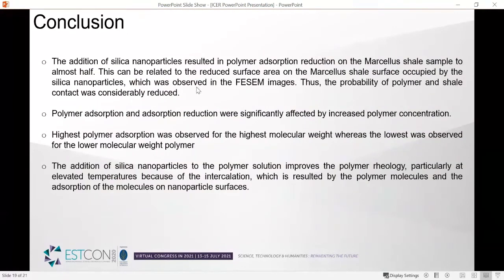And finally, the conclusion is that the addition of silica nanoparticles resulted in polymer adsorption reduction on the Marcellus shale sample to almost half, 50%. And polymer adsorption and adsorption reduction were significantly affected by the increase of polymer concentration. Highest polymer adsorption was observed for the highest molecular weight, whereas the lowest was observed for the lowest molecular weight, as can be seen from the last table.